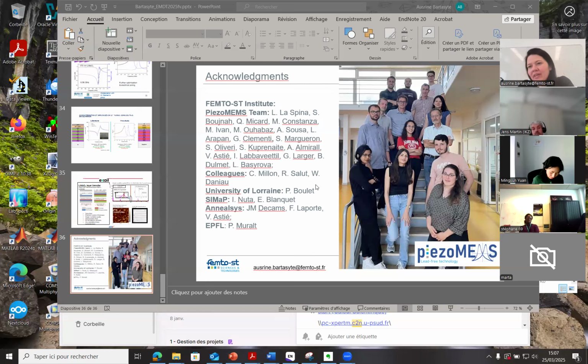So basically, you take different modes which have different sensitivity to the effect. For example, you have some modes which shift a lot with the stress, like the E mode at 380. So you take wave numbers that are little sensitive to the composition and estimate the stress. But you can also use X-ray diffraction. I coupled both. In X-ray diffraction, very frequently your composition shift is almost invisible.